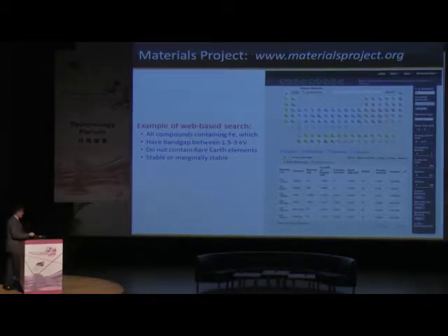I hit go, and it tells me there are 6 materials in the ICSD database, or in the database that they have currently, that have these properties. And I chose this basically because I knew hematite would pop up. This is sort of some properties you would want for a good photocatalyst. But what was surprising is that in addition to hematite, there's this iron fluoride compound that was sort of a surprise that one also has some interesting characteristics for this application. Okay, so that's the general idea, that the computation now is not going to just be running a code, but actually populating databases which are publicly available and can be used for materials design free of charge, completely open source.